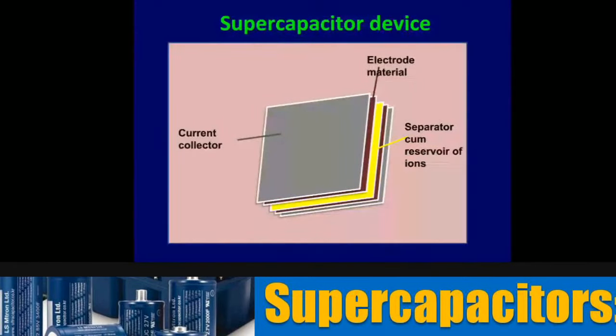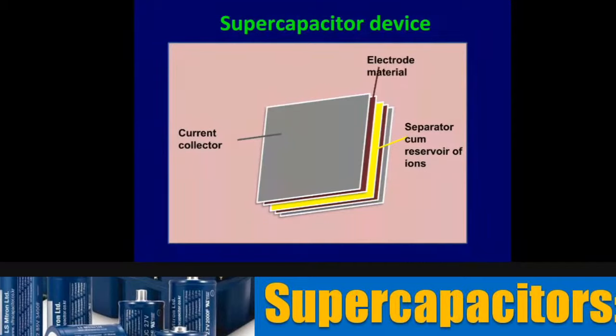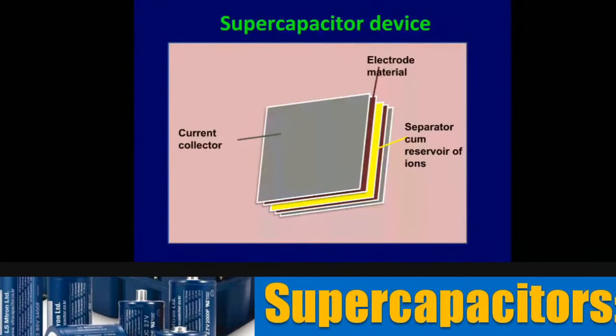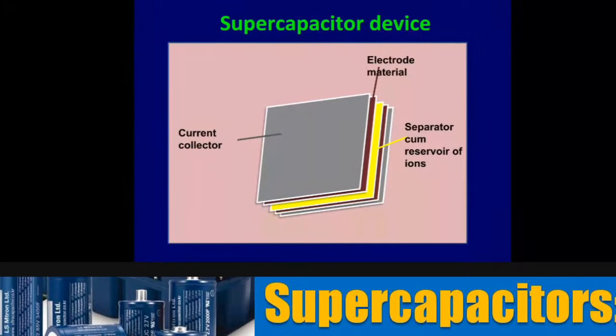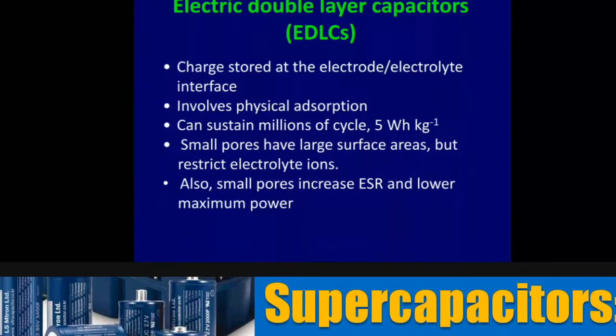What is normally being done is, in some cases, a cloth known as non-woven cloth. Normally, if you have a lens and look at our usual clothing, you will see an over layer and it's not strictly a two-dimensional thing. You can see the third dimension also. But these non-woven clothes are so flat that they don't offer any difficulty. And non-woven clothes are soaked in the electrolytes for few hours or even 1 or 2 days, so that they absorb the electrolyte and they behave as a reservoir and separator. You can see that the third layer is again the electrode material, the fourth layer, the fifth layer is the current collector.